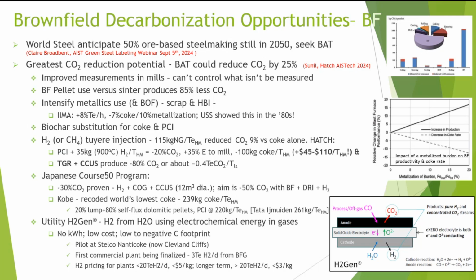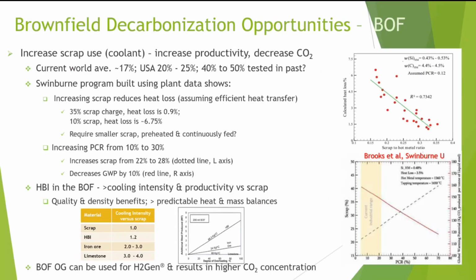This utility H2Gen makes hydrogen from water using the off gases from a blast furnace or even a BOF. They don't use energy, it's low cost, and it's a low to negative carbon footprint. They've run it at Stelco and Nanticoke, which is now Cleveland Cliffs and Lake Erie. Its first commercial plant is going in at 3 tons of hydrogen a day from blast furnace gas, and the hydrogen pricing is interesting. Less than 20 tons a day of hydrogen would be less than $5 a kilogram, but if you get bigger than that, it's going to be way less than $3 per kilogram. In fact, they were talking more like 1.5 to 2, which is perfect for the industry.